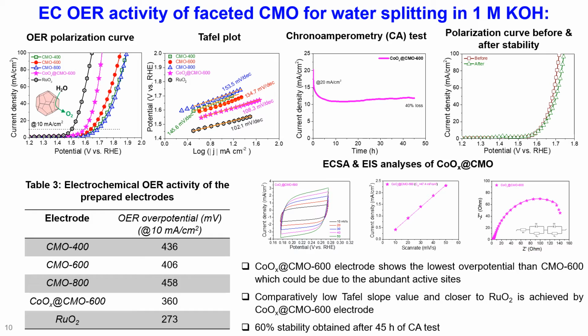We were curious to know about the OER activity of our faceted CMO electrodes in the same 1 molar KOH solution, so the OER polarization curve has been obtained for all three CMO electrodes. Among these three CMO electrodes, CMO 600 shows the better activity, with 406 millivolt overpotential at 10 milliampere per centimeter square current density, but which is quite large.